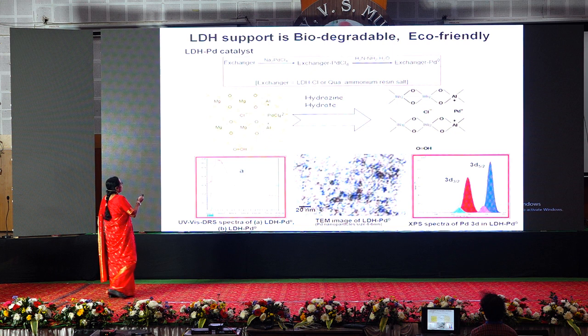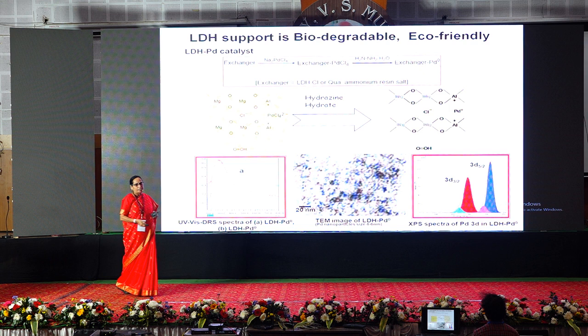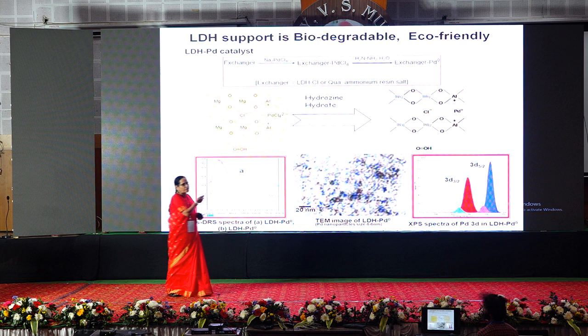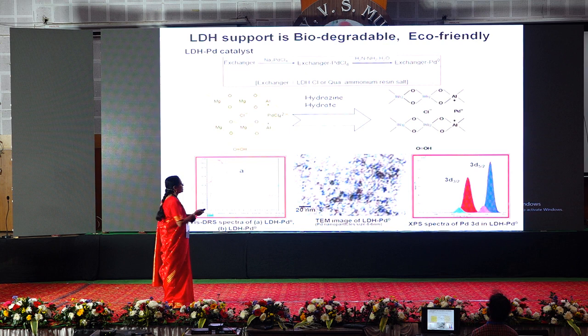And again, you can see there is a chloride, and you can replace it with tetrachloropalladate, and you will get the palladium on the hydrotalcite. And if you reduce it with hydrazine hydrate, you will reduce the palladium 2 into palladium 0. You can make this one.